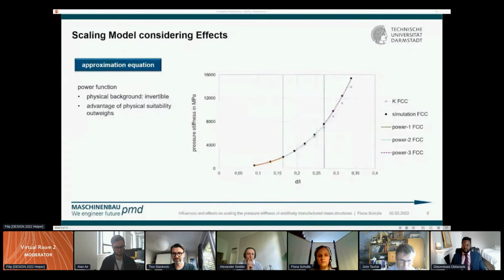Comparing the FEM and the analytical results of the overall as well as the partial stiffnesses reveals that for little d/L ratios, the framework's tensile compression stiffness is dominant, while for high d/L ratios, the bending stiffness increases more strongly and dominates the curve slope. Considering the different dominating underlying stresses for the stiffness, the approximation equation is subdivided into 3 parts, which show even closer agreement with the FEM results within their particular areas, as shown in the graph here.